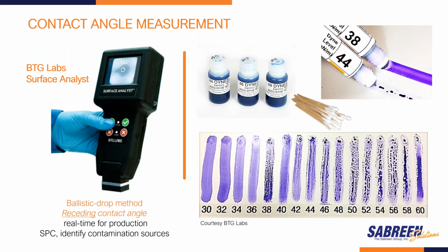If we start our testing at 30 dynes, or 32 dynes, or 34 dynes, 36, it looks like we're wetting. We test 38 and it doesn't work as well. Then we test 40 and we do see wetting. We can continue testing, get different results, and we can even try a 60 dyne solution, and wow, it looks like it is wetting. So what's happening here? Well, maybe we've put in too much dyne solution, and that affects the reading. We always want to be able to read the center of the liquid behavior, and it's also important to understand that aside from the thermodynamics, there's a kinetic effect.